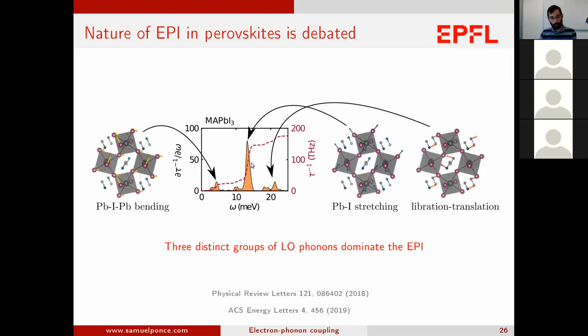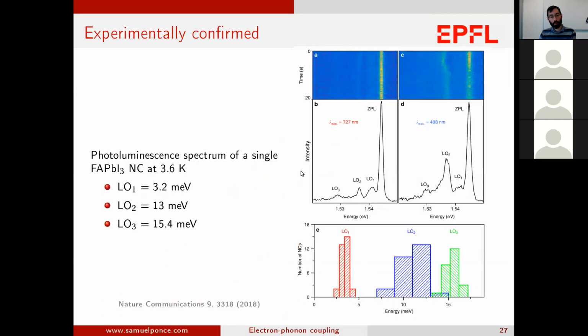And so this is what was shown in those papers. And what was quite interesting, and this was pointed out to me by Jackie, who is here at the 2019 APS March meeting, is that independently, almost at the same time, there was an experimental paper that was showing very similar results. Instead of MAPI, they were showing it for FAPI. So just the organic molecule is different. And here, again, they show that there are three dominant phonon modes. And the position of those modes are very close to the one that we predicted.